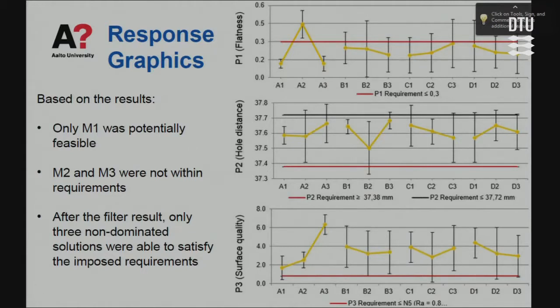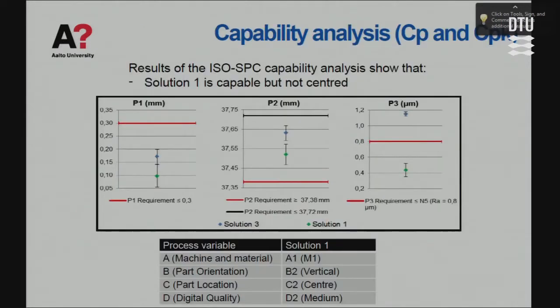And after we computed all the equations, all the objective functions, we filtered the results. Then we did the Pareto optimizations, and we had only three non-dominated solutions. So I moved on with that. What we did was to manufacture again. Here I'm presenting only 2 of the results of these non-dominated solutions. And you can see that when doing the validation phase, here again, requirement. This needs to be on target. This needs to be lower or equal. And this needs to be lower or equal.